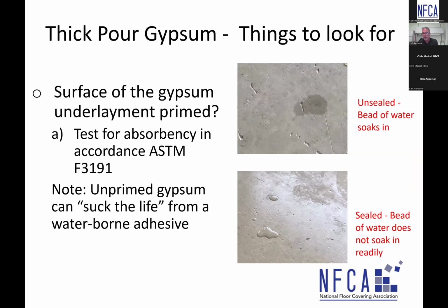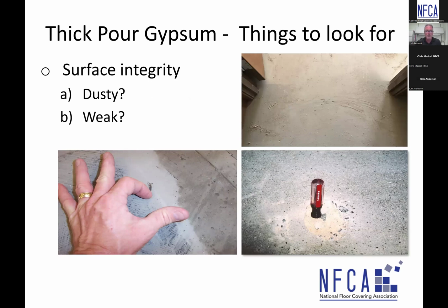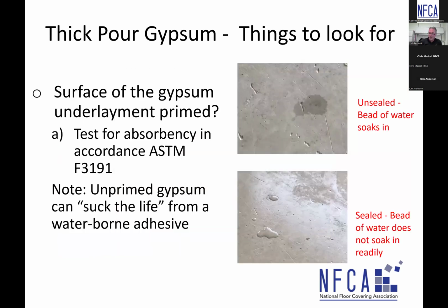But right out of the gate, when you do the water test over a primed surface, you will see water bead like you see in the picture here. Now, over the course of the next 3, 4, 5 minutes, it's possible that it soaks in. We see a dark spot. The water totally seeps in where we don't have glistening water. The point I'm trying to make here is unprimed gypsum, you hit it with water, it soaks in and it's gone. A primed surface, you hit it with water, and you should expect to see a bead like you see in the bottom picture there. One of many tests that should be performed prior to installation. Yes, excellent point.